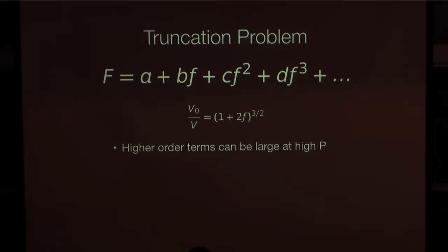That becomes really handy and important for the crystals and mineral phases that become very unstable out of their stability field. A good example is calcium silicate perovskite. The formalism was already developed in 1984 by Heinz and Jeanloz, so people have used it for the Birch-Murnaghan equation already. But there are also other problems, because the error bar tends to be very large at those conditions. Well, it's getting better, it's getting smaller, but it's still larger than the error bar you can get at V naught. So the whole curve suffers from the initial condition being more or less uncertain if you take that approach in certain cases.